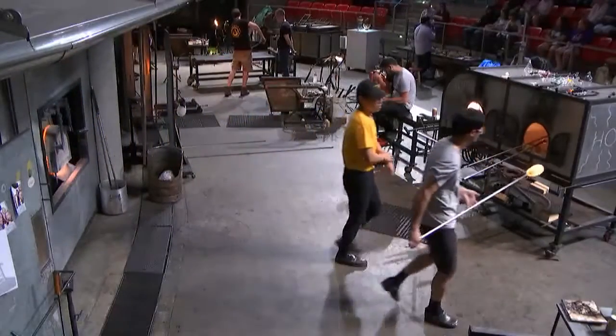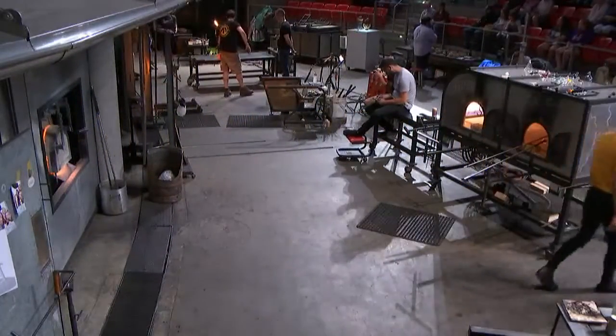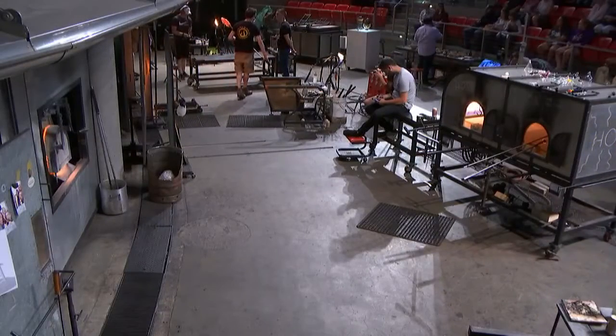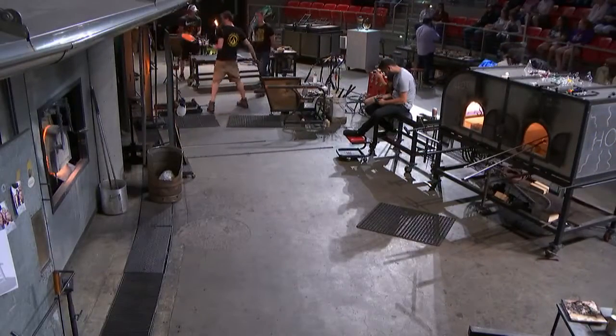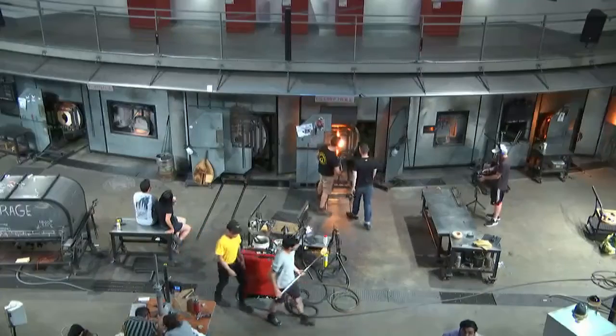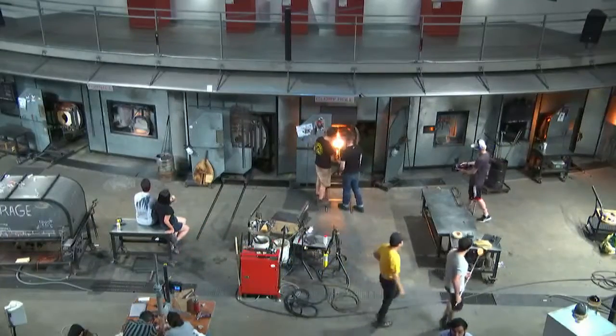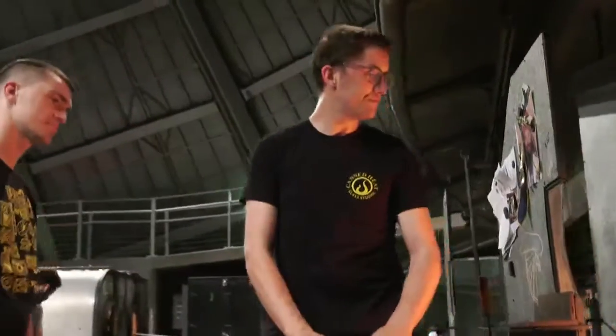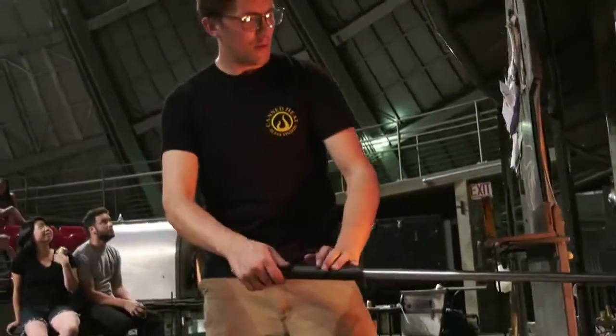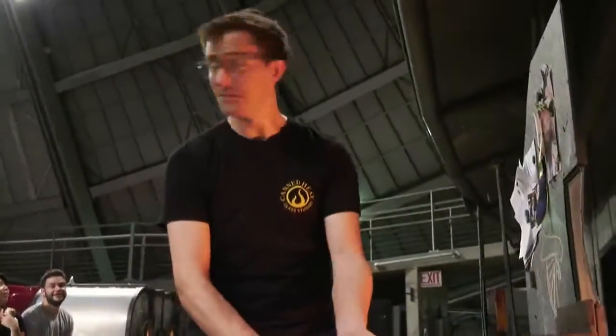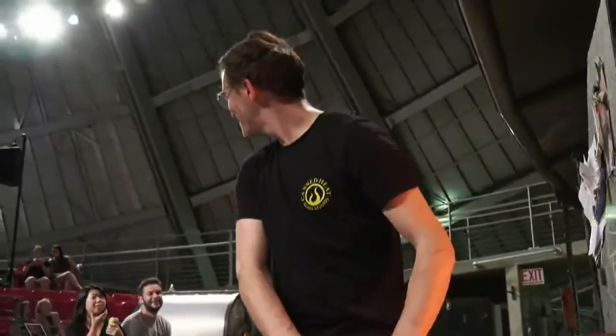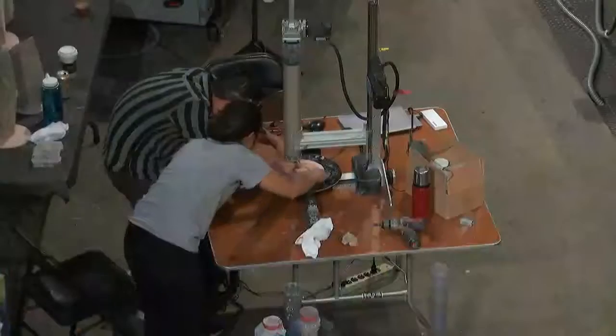Now, glass, when it's cooling down, shrinks less than 1%. It's not really noticeable. However, ceramic shrinks more than 15%, which can act like a snake and really constrict our glass and cause it to break and crack. This specific ceramic, however, won't shrink too much, and it shouldn't cause the glass to break itself. But again, we won't truly know until tomorrow once we bring the pieces out.